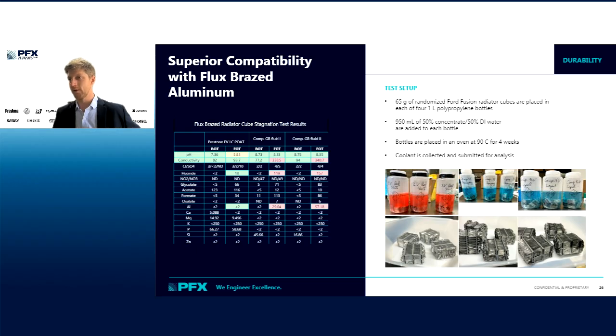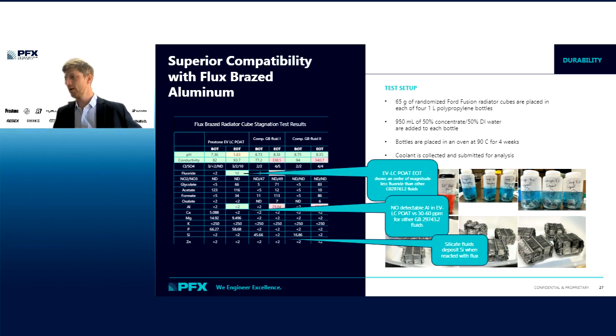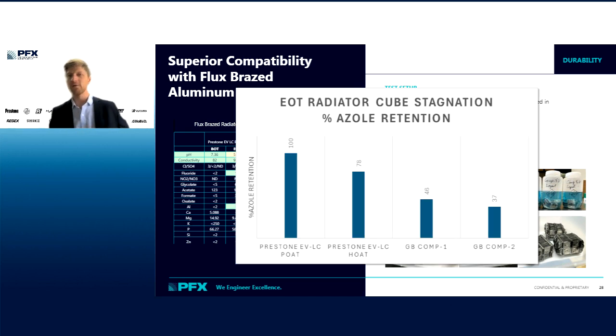And then finally, aluminum. That's another critical component for the corrosion aspects. No aluminum detected in our end of test fluid, where we have 30 and almost 60 ppm for the competitive fluids, respectively. One other thing to look at here is retention of azole inhibitors. Azoles are critical for yellow metal protection, your coppers and brasses. At the end of this radiator cube stagnation test, we retain 100% of our azoles for our POT fluid, almost 80% for our HOT fluid, versus competition where we see significant over 50% depletion for both of those fluids. So again, very robust fluids, particularly the phosphated OAT type fluid when we talk about resistance to flux brazed compatibility interactions.